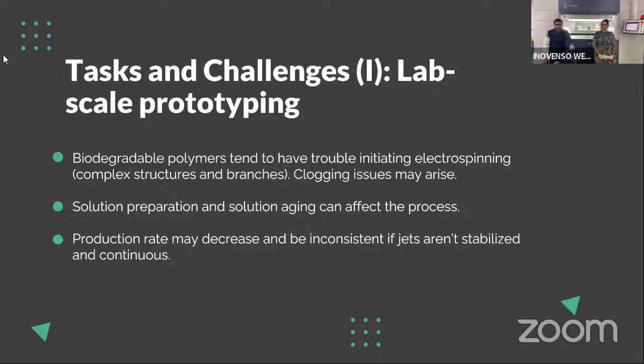Another issue is that if it's a bio-based and degradable polymer, solution aging could also affect the process. If you're going to set up a mass manufacturing site, you need to consider how you're going to produce the solution and electrospin it, because if you store the solution, the morphology of the nanofibers might differ or even worsen because of its degradable nature. So production rate may decrease and be inconsistent, of course. This is something you need to address at the lab scale before you worry about the industrial scale, so that you don't have these issues there, which I'll talk about on the next slide.